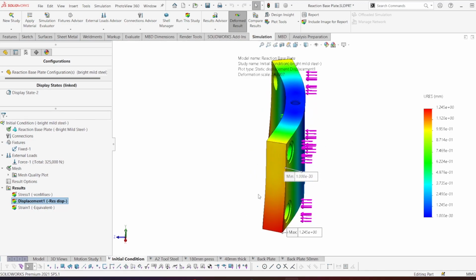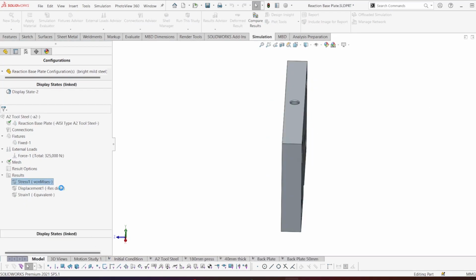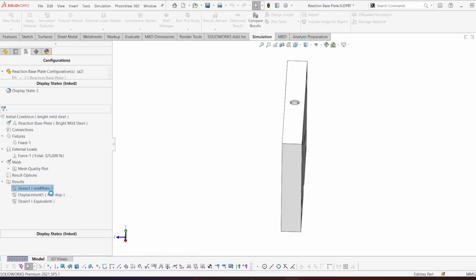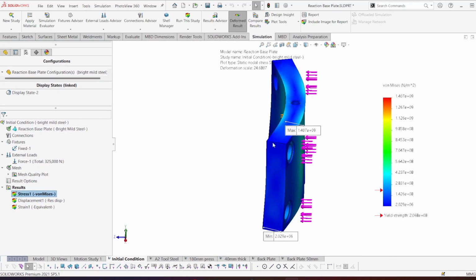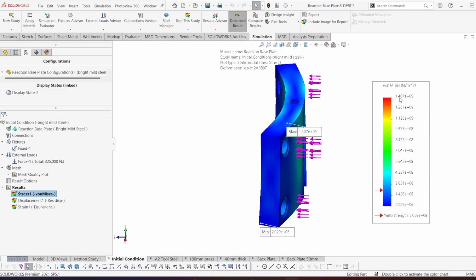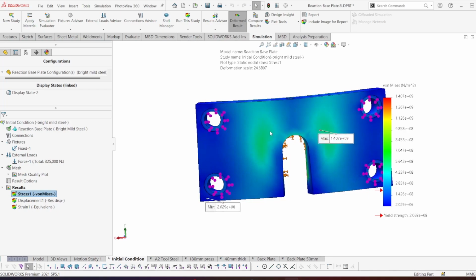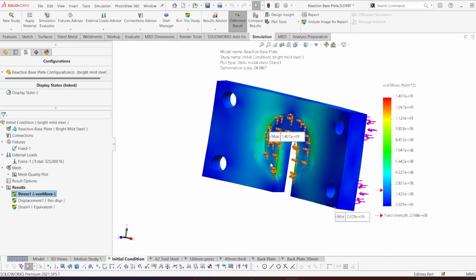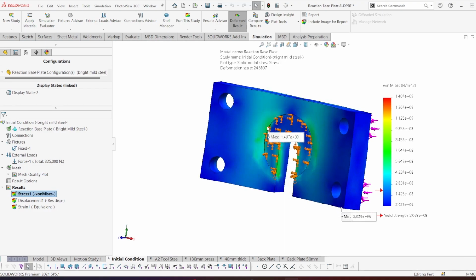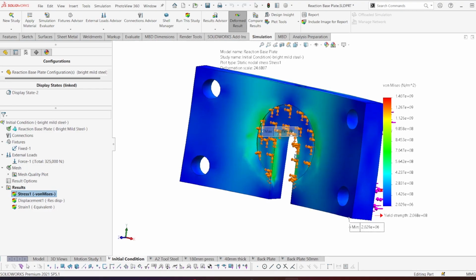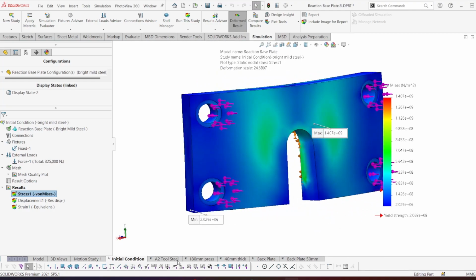So then the logical conclusion is, this is 32 mil thick, what happens if we go for A2 tool steel, which is what this is? So one thing to note with the previous configuration, as bright mild steel at 32 mil, this is experiencing about 1.4 gigapascals of stress, mainly localized in this area. That's mainly where the stress is, and naturally where the hydraulic press is hitting, which I've assumed to be 100 mil in this small area. You can see a lot of the highest stress is actually on the lip of that hydraulic ram, and also at the back area here.